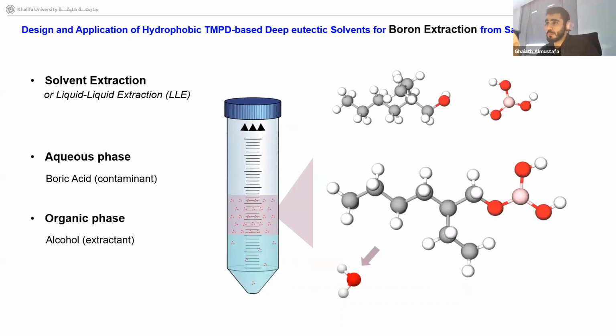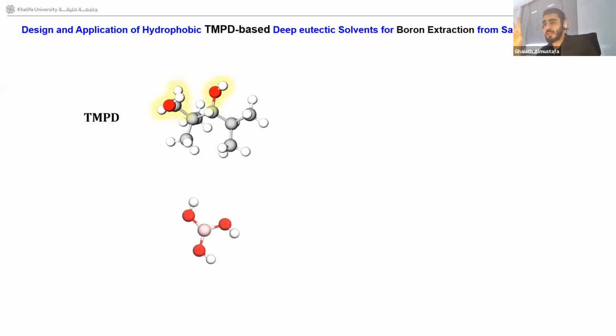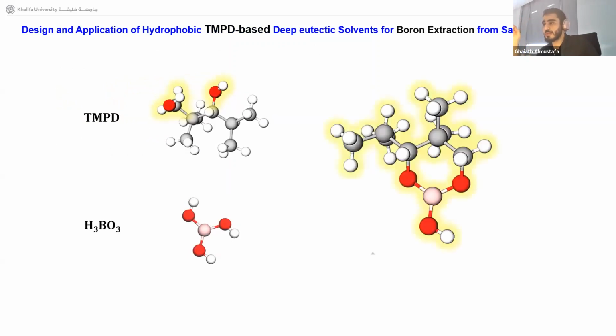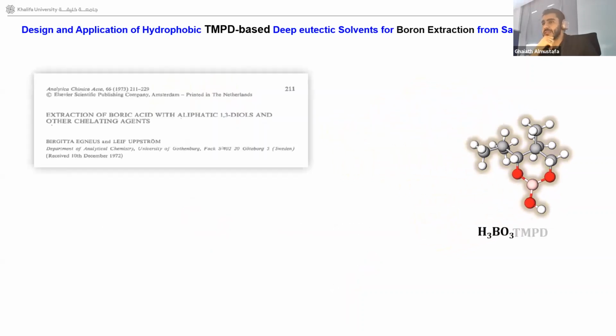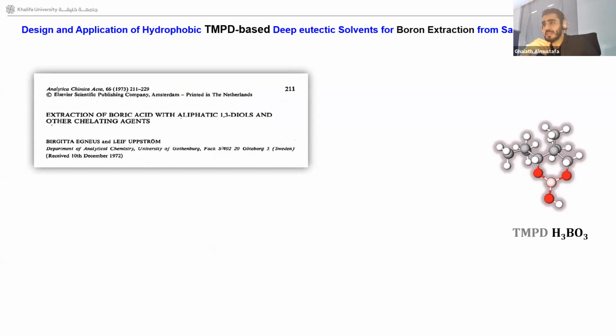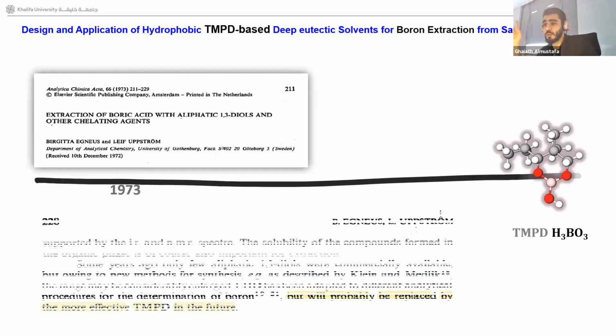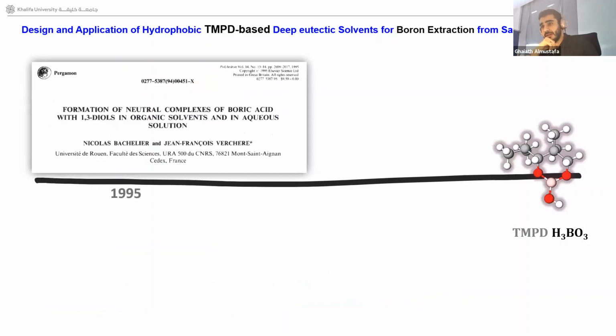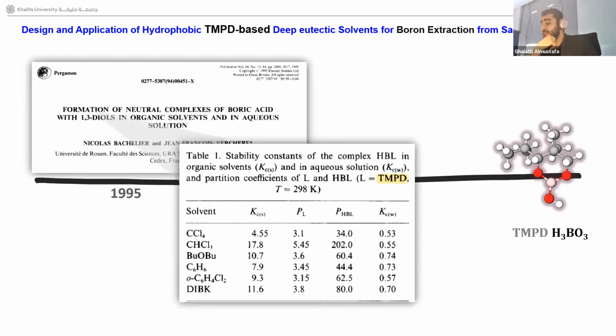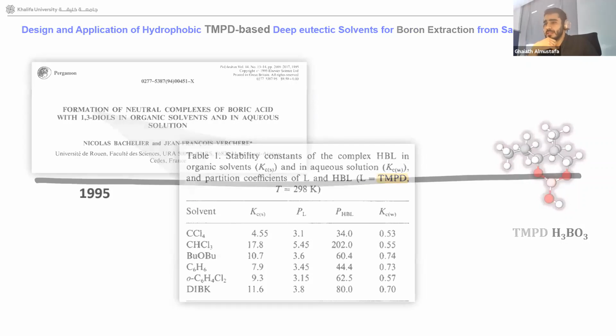Now, this brings me to my next term in that title, which is the TMPD, or 2,2,4-trimethyl-1,3-pentanediol. This diol particularly has two hydroxyl groups in such an arrangement that it allows it to form very stable complexes with boric acid. This TMPD molecule has been studied since the 1970s, and it was predicted back then that it was going to replace other boron extractants. Later in 1995, further studies used TMPD in different organic solvents and studied it for boron extraction, where it showed high stability constants and very efficient extraction efficiencies. And the studies piled up since then.